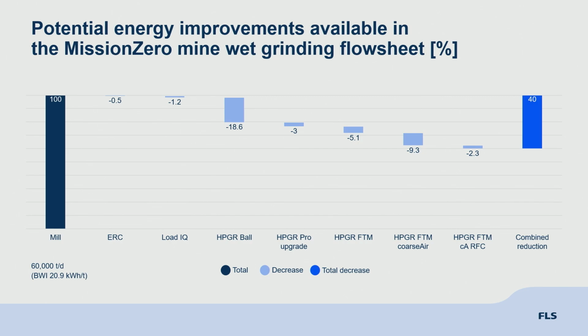So what we did is we took a conventional flow sheet and we called the mill 100% energy. And then we started taking out bits of conventional equipment and replacing it with our new equipment. So we took out the gyratory crusher and we replaced it with an ERC, which gave us a 0.5% reduction.